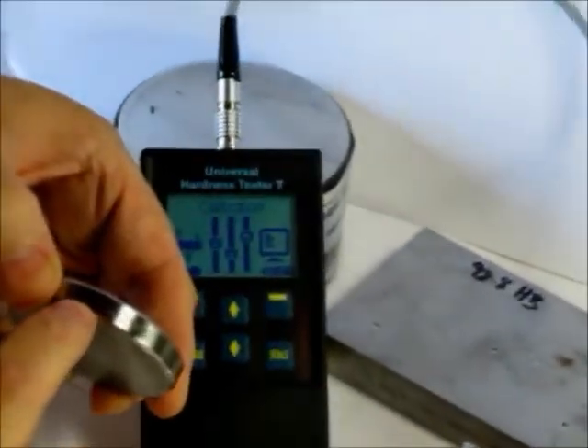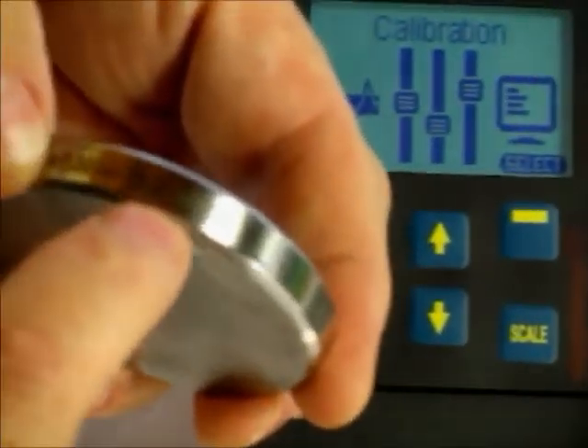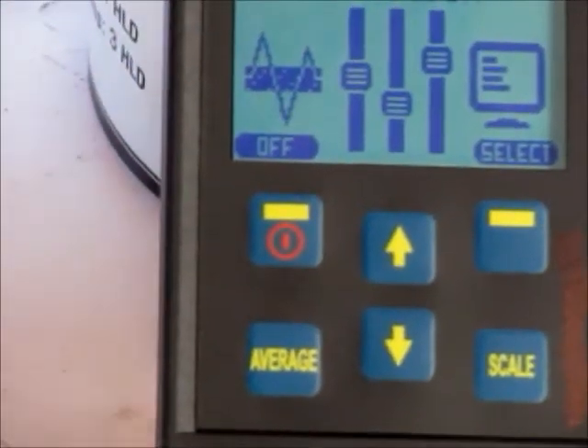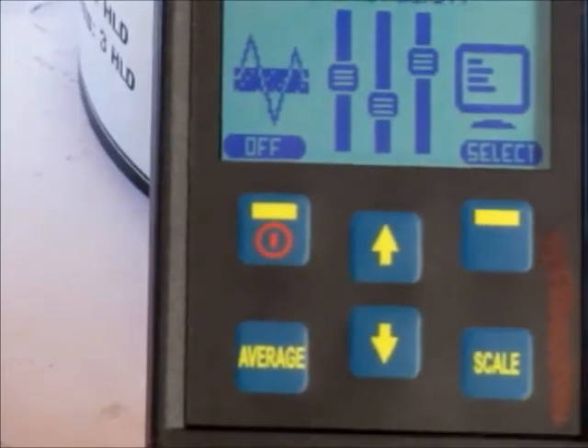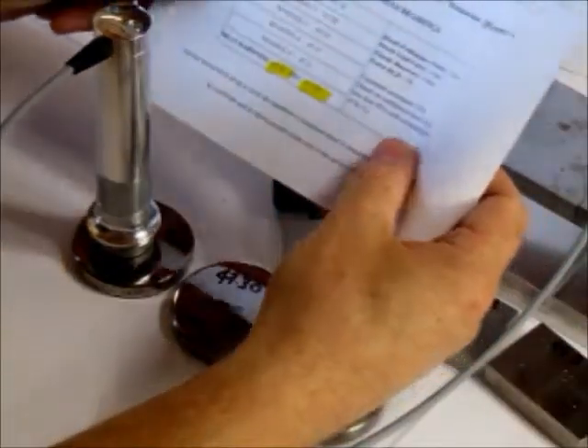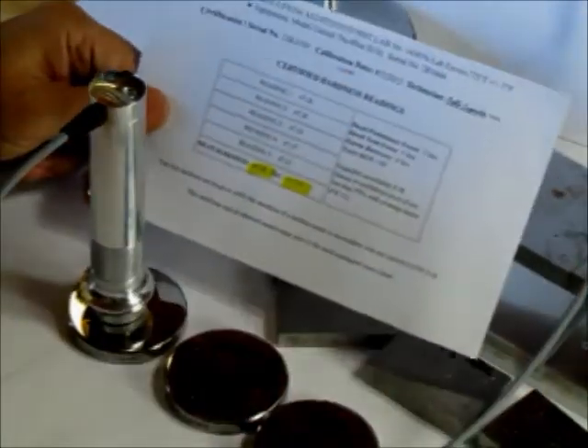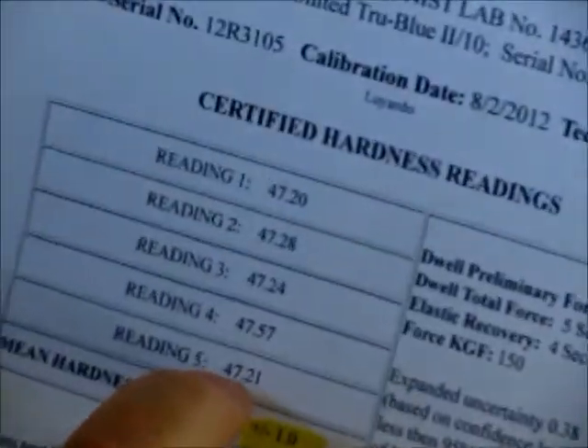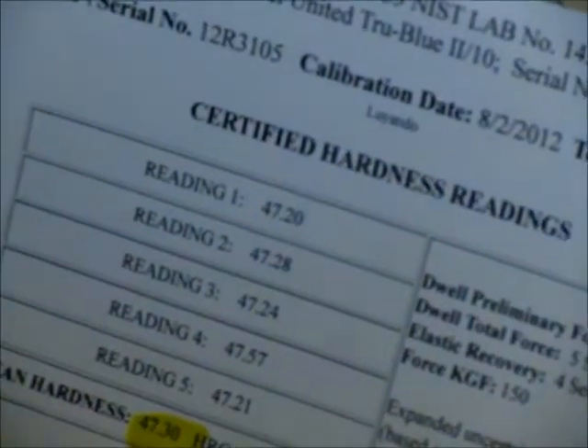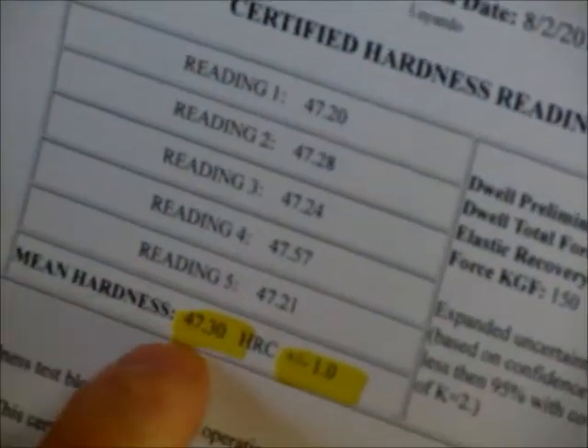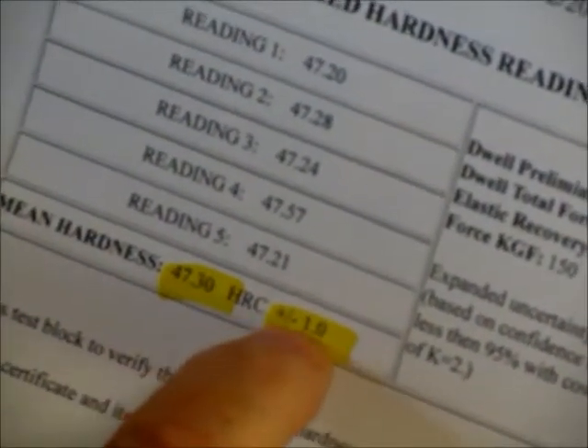This is this 47.3, and then it's plus or minus 1 HRC, so very accurate, but we do have an error in the test block, of course, based on the hardness or the mean across. And with these test blocks comes the NIST calibration certificate. This is one that I printed out, and it shows that when this was tested, the readings were 47.20, 47.28, 47.24, 47.57, and 47.21. And so that the mean hardness is 47.3 with a variation of plus or minus 1.